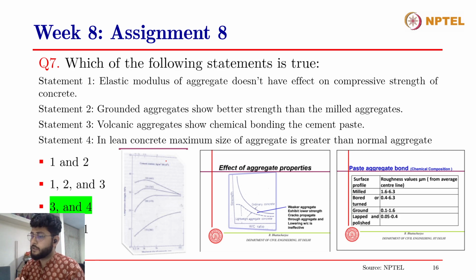If you have a concrete with aggregates having a lower elastic modulus, then they will be taking a lower share of the load, and the majority of the load will be taken by the cement paste and the ITZ. Therefore that will break faster, because the ITZ is taking a majority share of the load, and that will lead to a lower compressive strength of the concrete. So this statement is not true. Elastic modulus of aggregate does have an effect on the compressive strength of concrete. So this is a wrong statement.